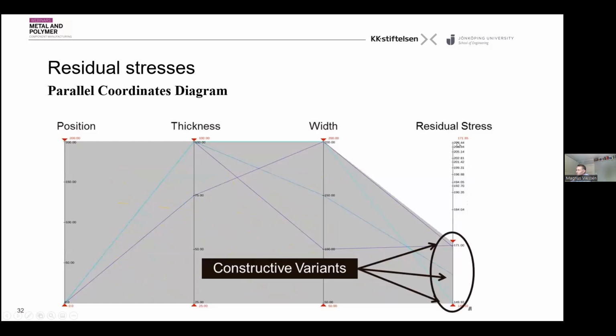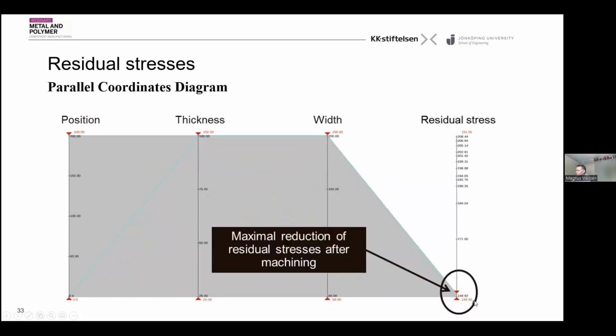Then again you can simply drag this line and find the ones where you have the lowest residual stress. From the beginning you could have 208, and you can get down to 150 megapascals in the residual stress of the machining. This is, again, a very simple case where, instead of playing around with manual optimization, you can do quite a small amount of extra work and get much more information to reduce the problem of cracking when you do the machining.